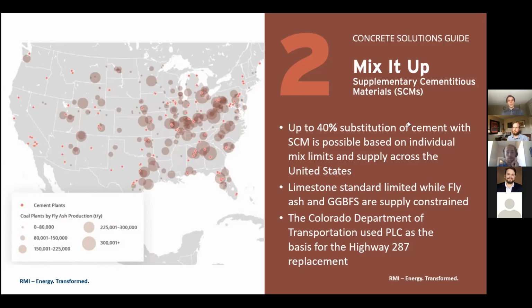So what that means is that even though the amount of fly ash used in concrete has stayed relatively stable across the US at around 15 million tons per year, the fraction of total fly ash that's being used is increasing because the supply is dropping off. So at the moment, around 50% of the fly ash that is produced across the US is used, recycled into producing concrete.